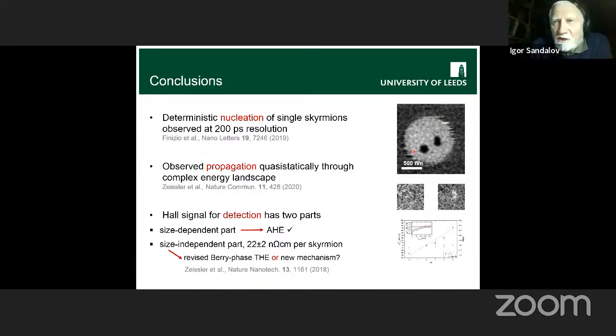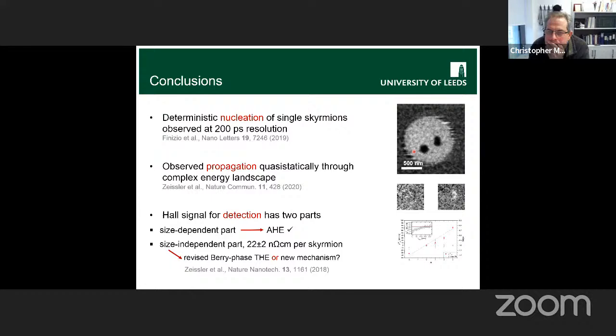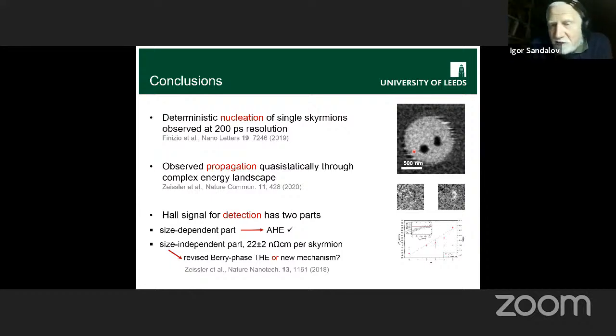Well, the question actually arises because all these theoretical calculations are usually based on micromagnetic simulation, where quite strong assumptions are used. And when you make these experiments with light, different materials have different matrix elements of interaction with light, and correspondingly different rotation angles in this experiment with rotation of the polarization plane. And this does not exist in this kind of simulation, right?